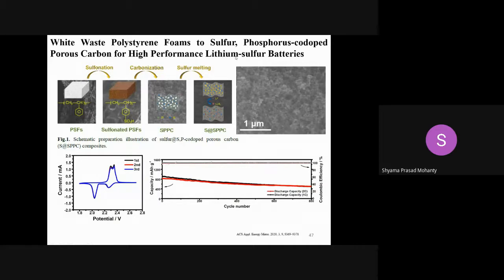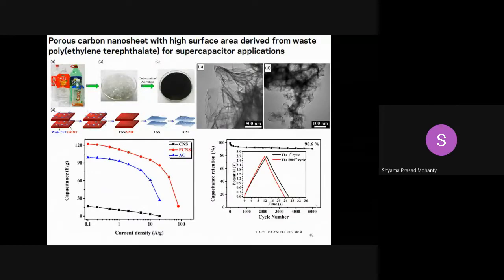Okay, so that one was then utilized to contain the sulfur, and it was used in lithium sulfur cells, and the cells were stable till 800 cycles, and they retained very high coulombic efficiency. Okay. So we discussed SPPC, and some applications in lithium sulfur cells.